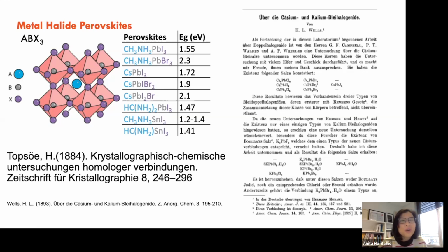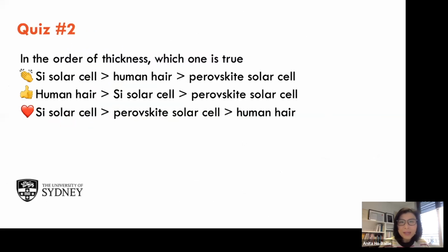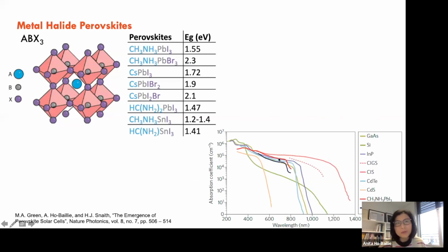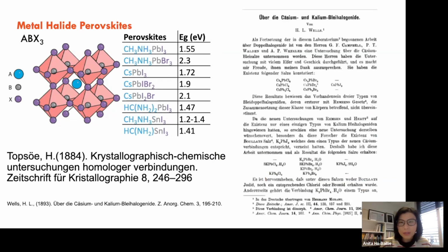Now, people didn't know about the crystal structure or photoconductivity until 1958, and they were looking at it for LED use. They didn't think that it could be used for solar cells until 2010, during our lifetime. Because it has a very good optical absorption coefficient, meaning how deep the light can be absorbed, it doesn't need a lot of material to absorb the light. You can see the metal halide perovskite is red and black, and they are much better than silicon, which is green. What it means is you can make it into really thin material.